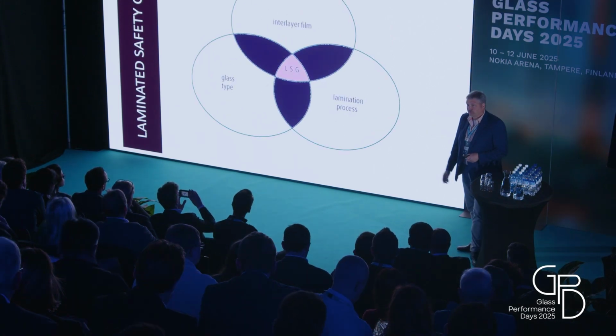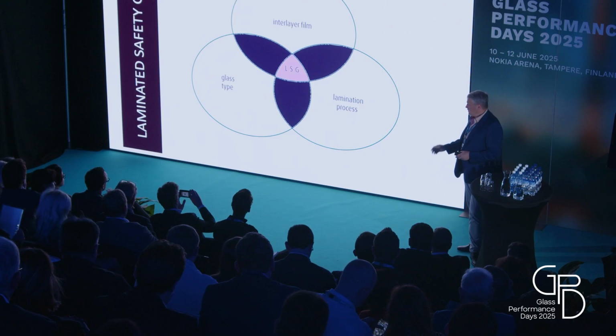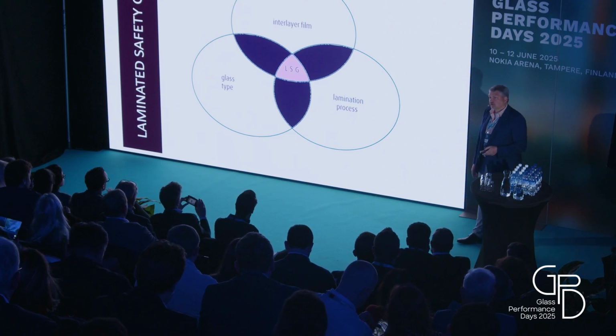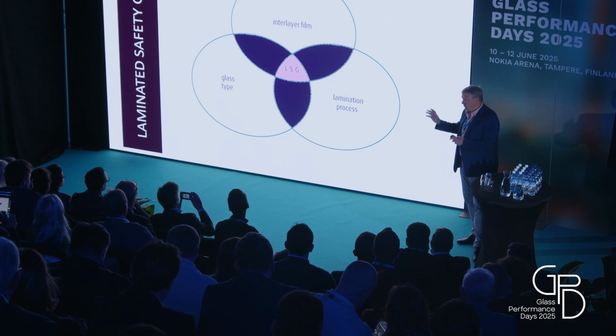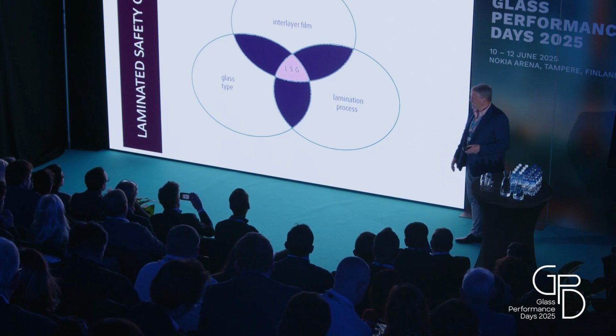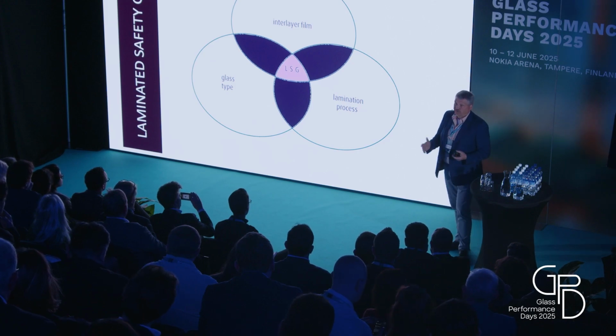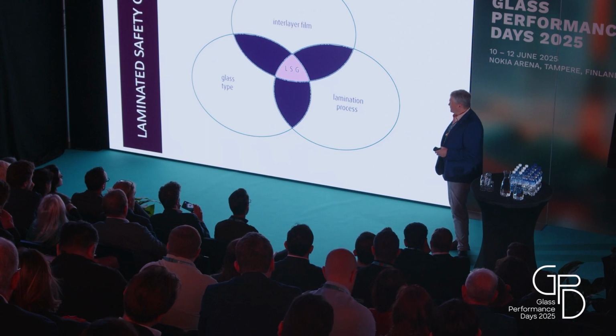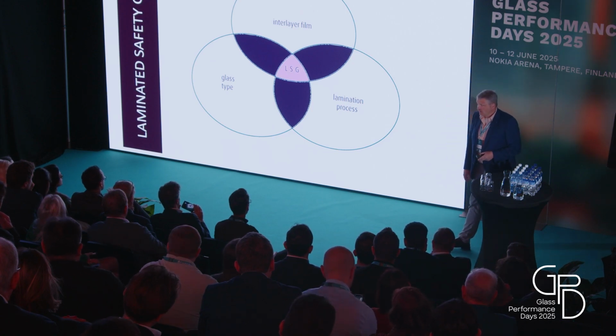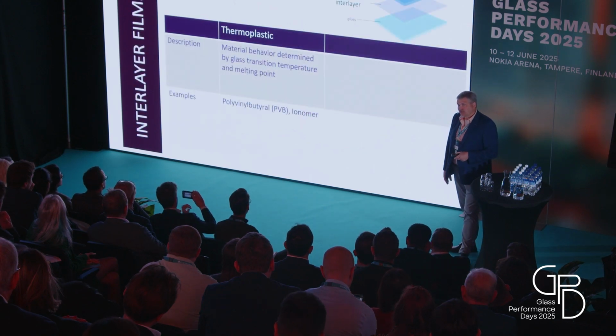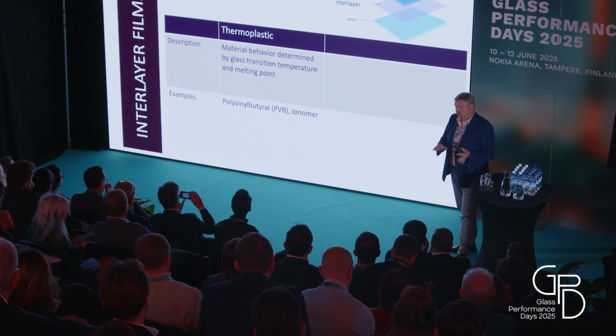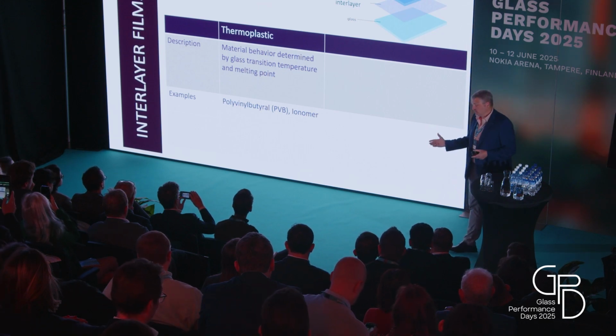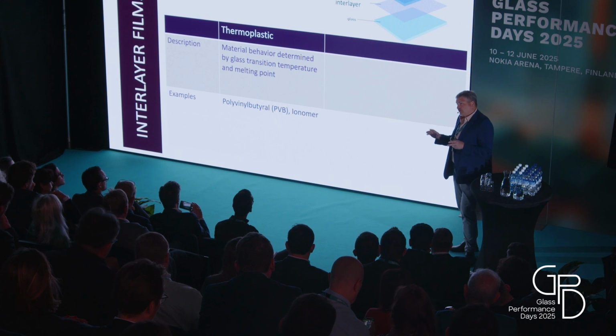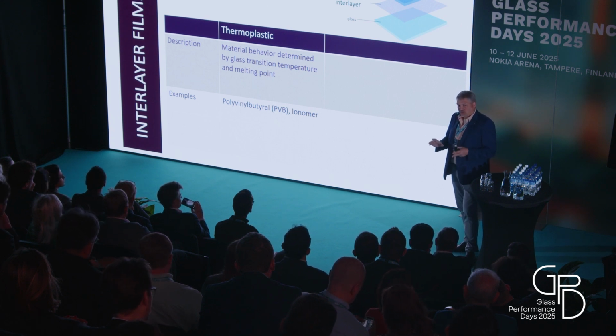If we want to make good laminated safety glass, then we have to focus on 3 parameters. You can see here, of course, the glass type, the lamination process, and of course, the right interlayer. And if you want to make a good laminated safety glass, then for sure you have to find the right combination out of it to match your or your customers' targets. I want to focus on the interlayer films today. Therefore, I will give you a short introduction into the different types of these films. We heard about interlayer films that are thermoplastic already. As you can see here, PVB or ionomeric are polymeric films that we call thermoplastic. Means they are characterized by the so-called glass transition temperature and the melting point.